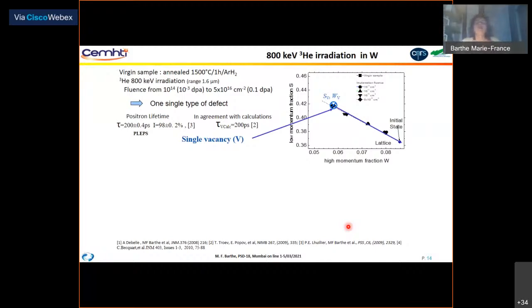So in the first study, we implanted tungsten using helium-3 at 800 keV, with different fluences from 10^14 to 5×10^16 per square centimeter.